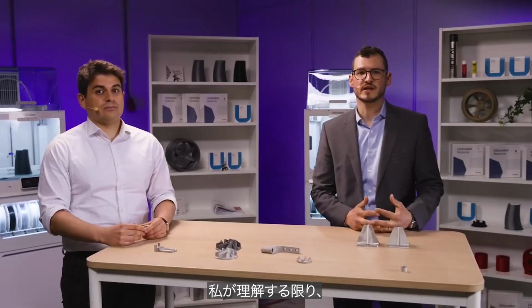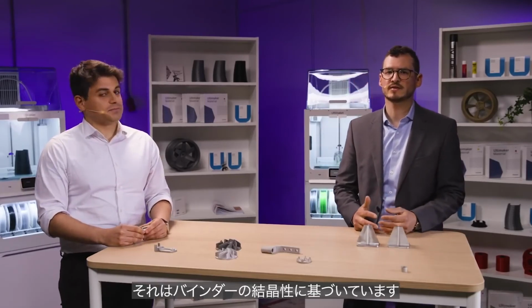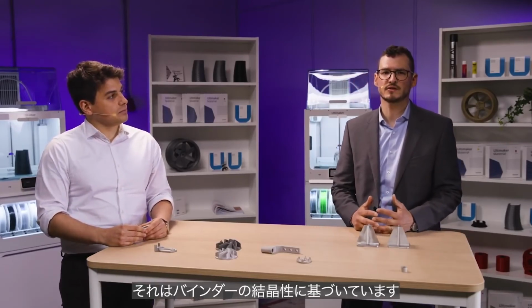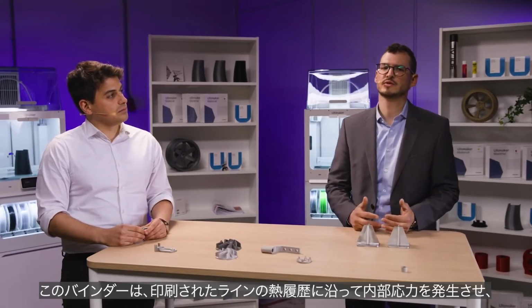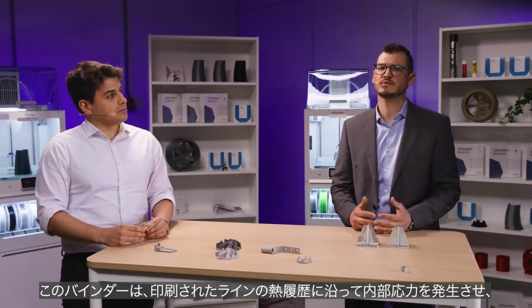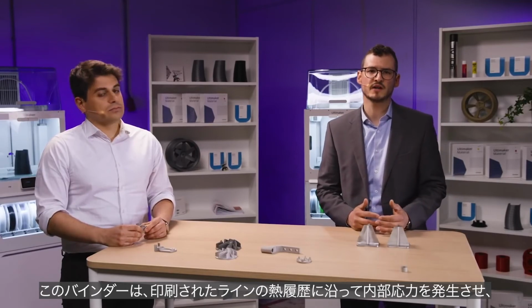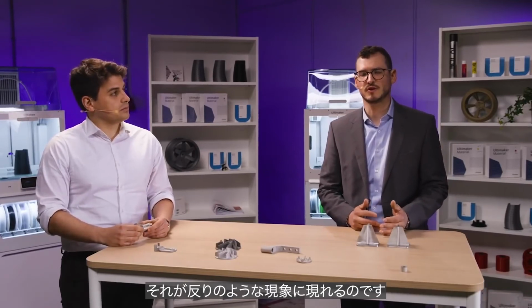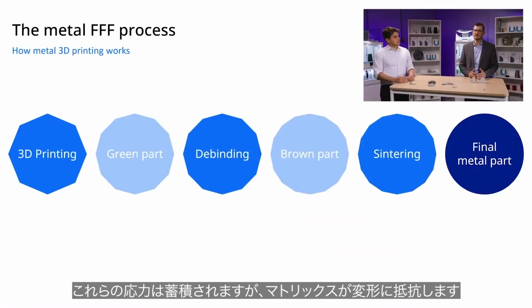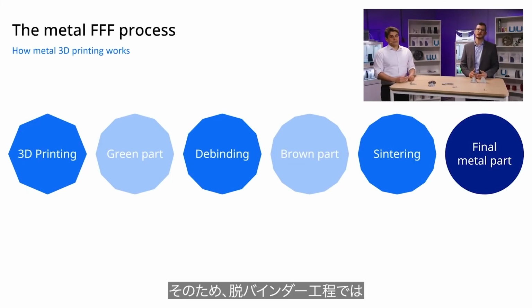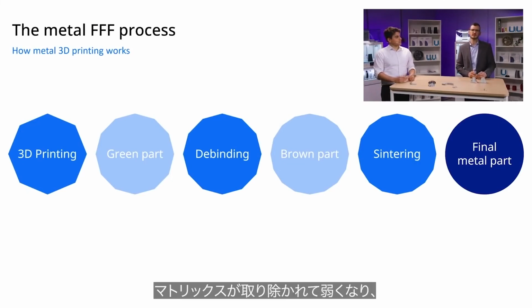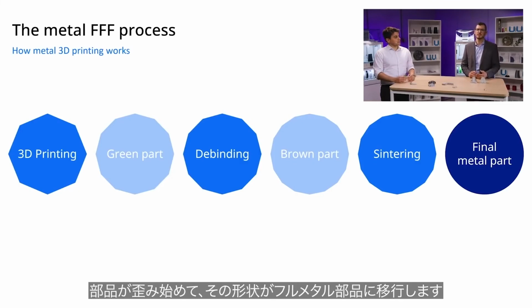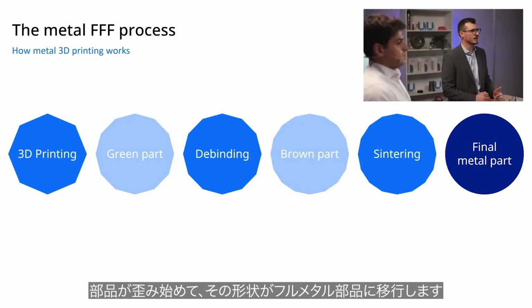So, as far as I could understand it, it's based on the crystalline character of our binder, which introduces internal stress along the thermal history of the printed lines in the part, which could also be seen in phenomena like warpage. In the green state, these stresses are stored, but the matrix resists the deformation. So during the debinding steps, the matrix is removed and is getting weaker, and the part starts to distort, and the shape is transferred into a full metal part.